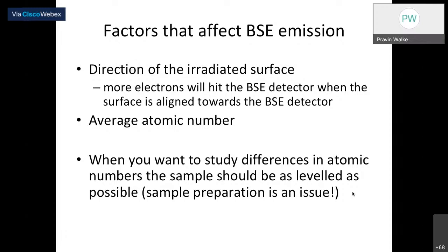What are the important factors? Same as SE, there are some factors which affect BSE emission. For example, let's look at the direction of the irradiated surface. More electrons hit the BSE detector when your surface is aligned toward the BSE detector, or you have to tilt your specimen a little bit so that you get more signal to the BSE detector and get the BSE images. So why are BSE images important? Why are SE images important?